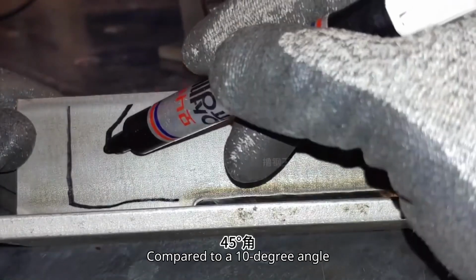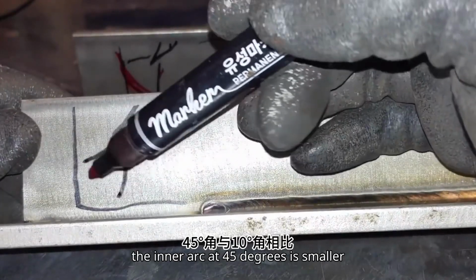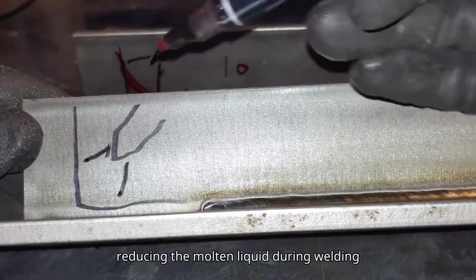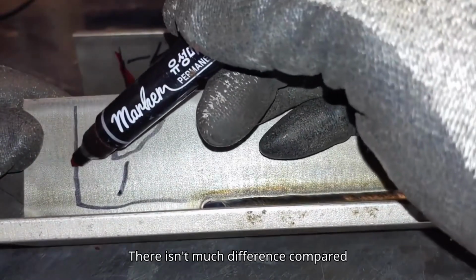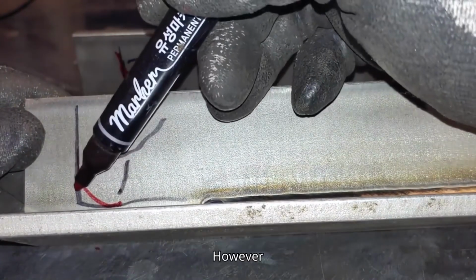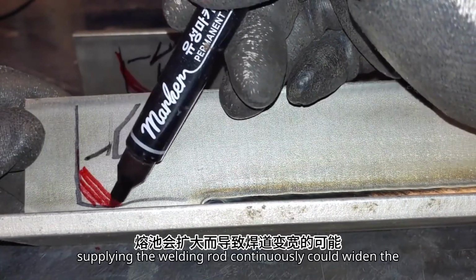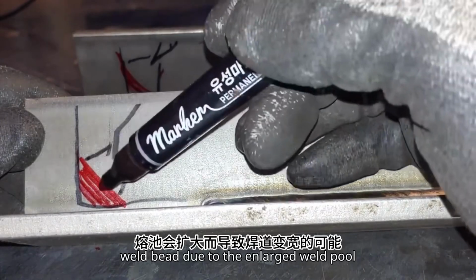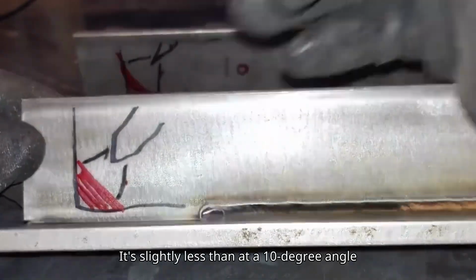Compared to a 10-degree angle, the inner arc at 45 degrees is smaller, reducing the molten liquid during welding. There isn't much difference compared to the 10-degree angle. However, supplying the welding rod continuously could widen the weld bead due to the enlarged weld pool. It's slightly less than at a 10-degree angle.